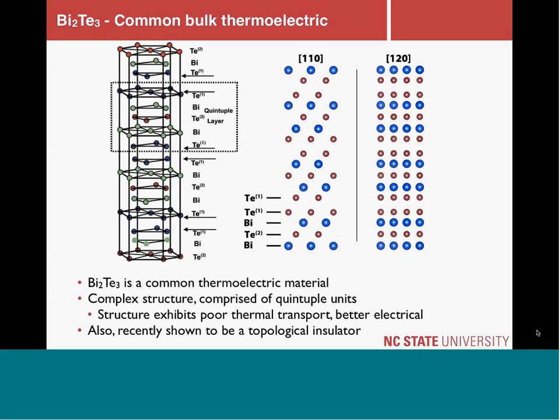Right. Now, the bismuth telluride structure is rather complex. That's a single unit cell that I'm showing there. That hexagon, that big one there, is a single unit cell, and it's comprised of quintuple layers. So there are these five-atom atomic plane stacks that then feed material. I don't know if my cursor shows up on the screen or not, but they're terminated by the Te1 layers.